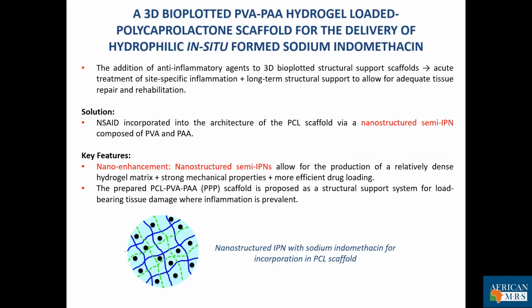The first example here is a 3D bioplotted PVA PAA hydrogel that's a scaffold for the delivery of indomethacin, which is an anti-inflammatory. So the addition of your actual anti-inflammatory agent to your 3D bioplotted scaffold allows for the acute treatment of site-specific inflammation, as well as providing structural support long-term to allow for tissue repair and rehabilitation. So what was actually designed is this scaffold, which was then nanostructured via a semi-interpenetrating network composed of your PVA and your PAA.